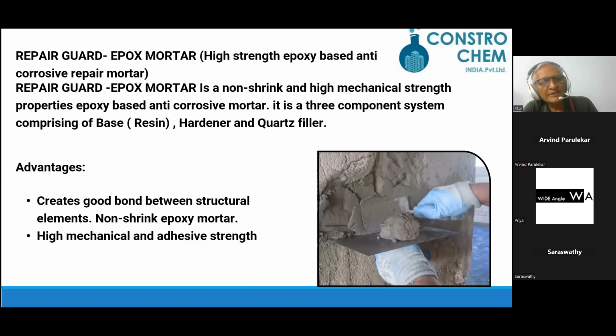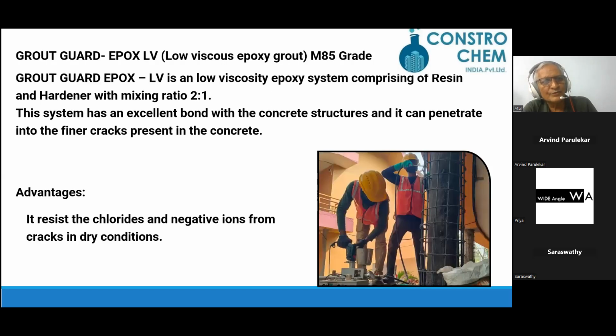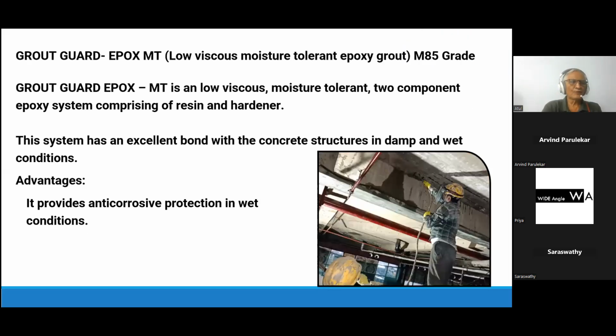It is a 3-component system comprising of base, hardener and quartz filler. Advantages: creates good bond between structural elements, non-shrink epoxy mortar, high mechanical and adhesive strength. Grout Guard Epoxy LV is a low viscosity epoxy system comprising of resin and hardener with a mixing ratio of 2:1. This system has an excellent bond with concrete structure and can penetrate into the finer cracks present in the concrete. Advantages: it resists the ingress of chloride ions.